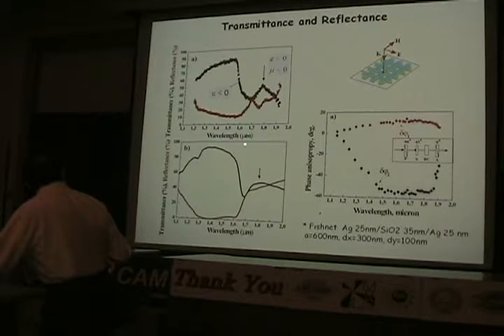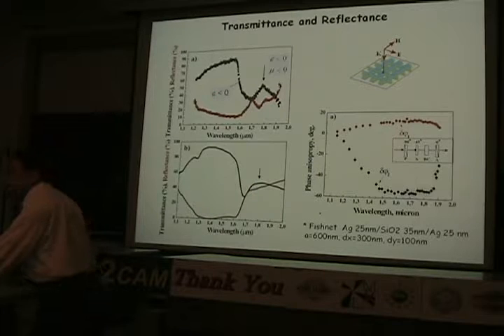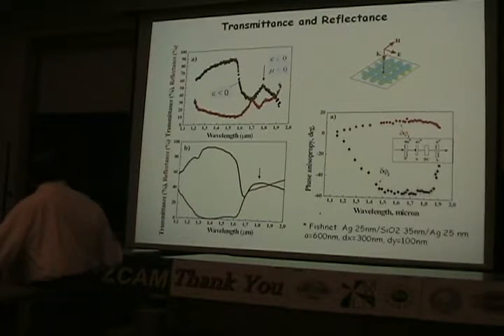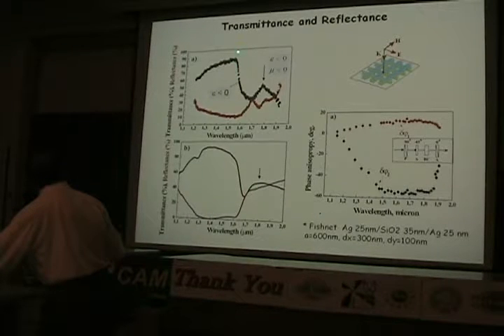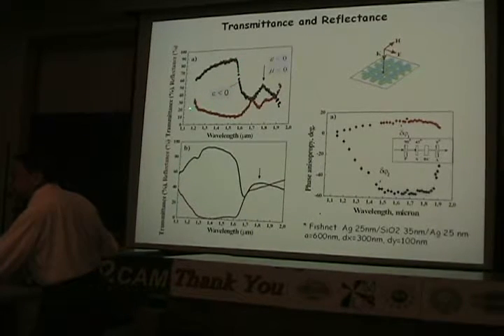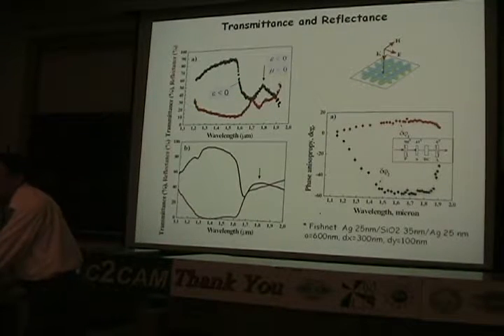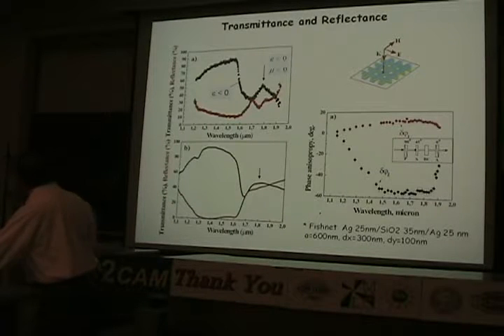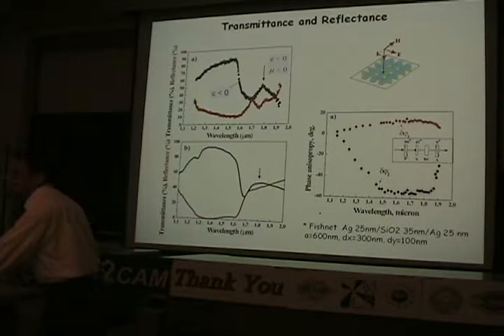Here is some near the magnetic resonance. And below this, we still have mu larger than 0. But the plasma frequency is here somewhere. So above and below that plasma frequency, we will have epsilon less than 0. But in this region, mu is larger than 0. So again, the refractive index is imaginary. If the refractive index is imaginary, the wave is an attenuated wave. It's not a propagating wave. So the wave gets attenuated in this region.